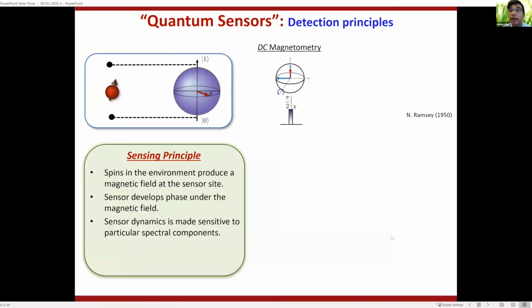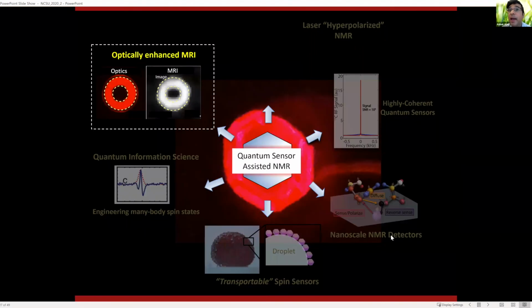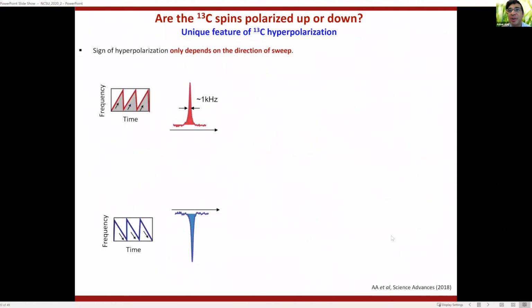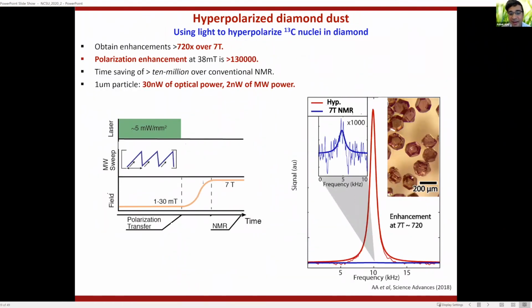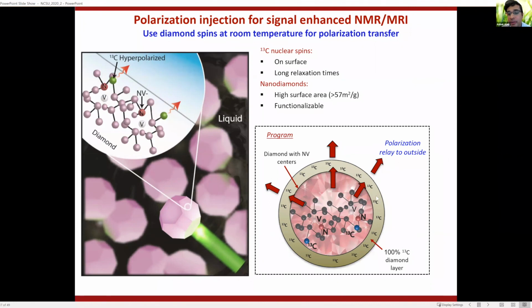Oh yeah, so this I should caution. I don't want to give the wrong impression. We haven't done it yet, and we haven't tried much too. All this is fairly new. But what we want to do is, because of this T1 reason that we were just discussing, we are liaising with growth experts and growing diamond on diamond. So that's our strategy. We polarize the carbon in the diamond, and then we grow ultra pure diamond, so this is diamond with no defects, basically because inside the diamond you've made these NV centers and they're full of defects, and this is what causes